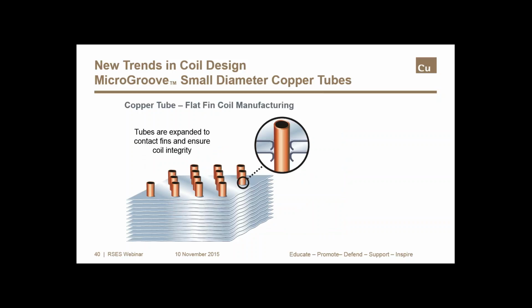A rod, or what's referred to as a bullet, is physically forced through the tube. The bullet is a bit larger in diameter than the tube, and the expansion of about 10% or so does the job. With a trend towards smaller diameter tubes, this process has certainly been doable, but it's become a more delicate and slightly longer process than it is for larger diameter tubes.